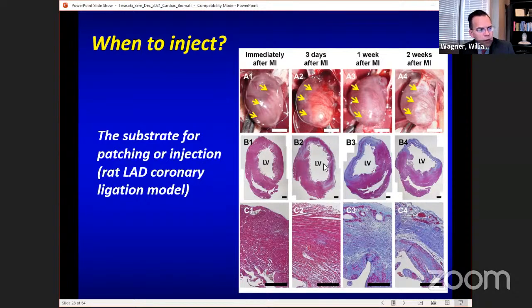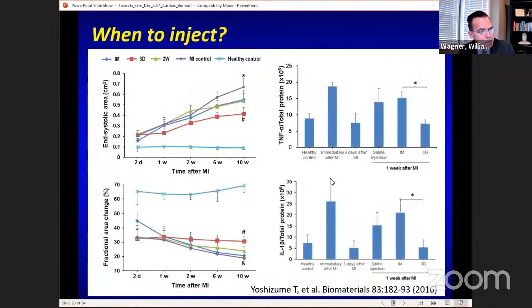And you can see the substrate that you're injecting into is quite different. So this is what the heart looks like that you're injecting to. And you can see at 2 weeks that you've got a pretty well-developed infarct there. At immediately post-MI, it still looks okay. You haven't had the necrosis and the inflammation set in yet. And here at 3 days, you begin to see that happening. So here's the data. It's a little bit confusing.